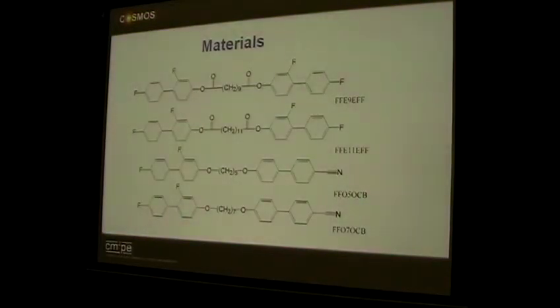We do make a lot of ferroelectric and anti-ferroelectric materials, but they tend to be for the bistable displays. A ferroelectric is bistable, but it doesn't give you grayscale without time dither or field dither. The anti-ferro does. That will give you grayscale with V-shaped switching. But you've got a problem unless you use the high tilt. That's another lecture I can give you, the high tilt anti-ferros. You always have alignment problems, I think, with the ferroelectrics. These flexos, you use conventional alignment. They use rubbed nylon, polyimides. PVA will work. There is a process you have to go through. When I come to the next lecture, you'll see how good the alignment can be.